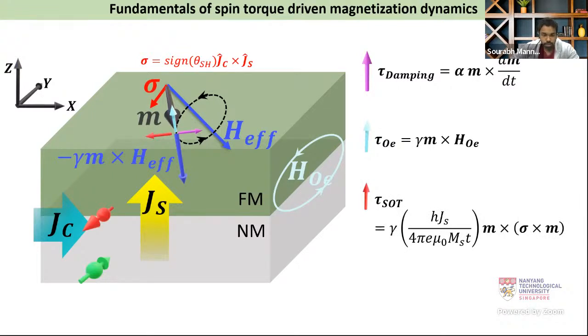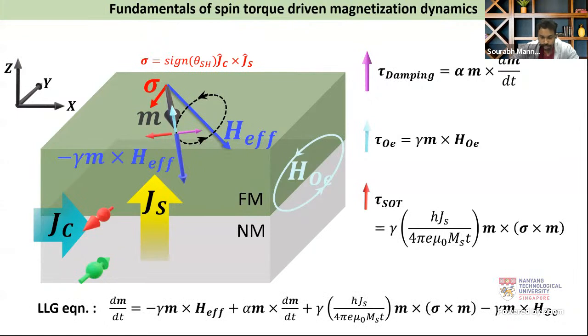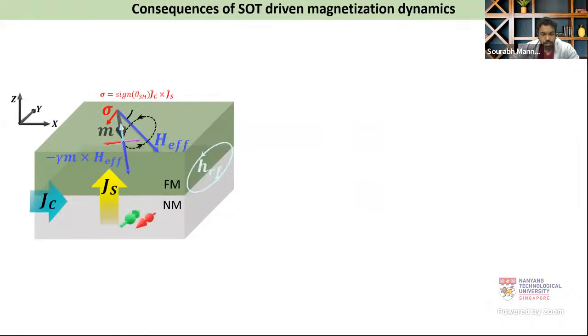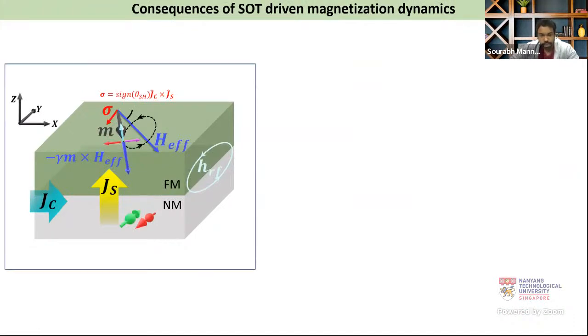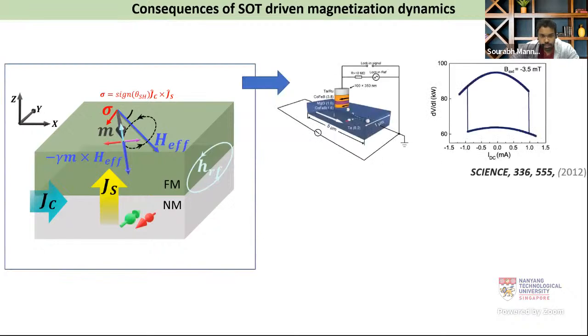So with all this torque, the magnetization dynamics can be quantitatively expressed by the Landau-Lifshitz-Gilbert equation, which is shown here. The consequences of this spin orbit torque driven magnetization dynamics are several. Among them, it can switch the magnetization to the spin polarization direction, as is demonstrated by this paper.